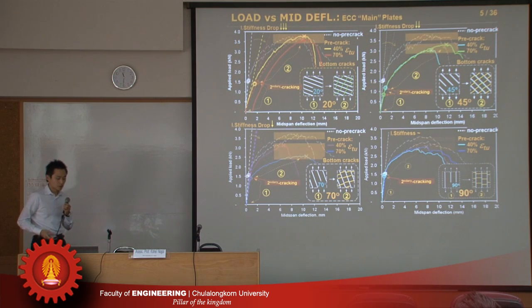So I show you the load displacement curve of the bending test of the plate with initial damage with 20 degrees cracking, initial crack, 45, 70, 90. So many lines on it, but this white line is the non-damaged case. And these colored lines are the results with damage. So for example, when we see the 20 degrees, we see the reduction of the stiffness, right? From the white one to the yellow one, but we do not see so much on the strength.